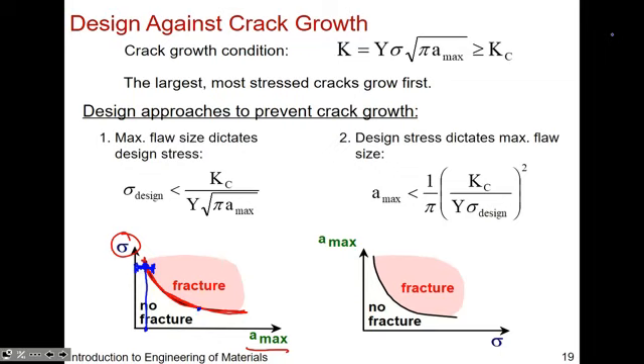Now, if you're in this regime, the error bars in real life tend to be like this, okay? So let's say that's your data point. Statistically, you could fail because it could be out here as well. So when we get to this applied stress, it's less certain. So even though it's a much lower applied stress, you'd think it's probably not going to fracture. That's actually not so true. What typically happens is when you engineer the material, you rate it a little bit more safely. You say, okay, just don't operate under these conditions. But anyway, we'll get to a plot that looks sort of like this as well.